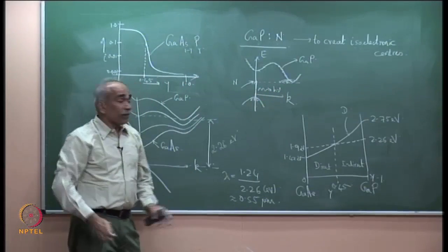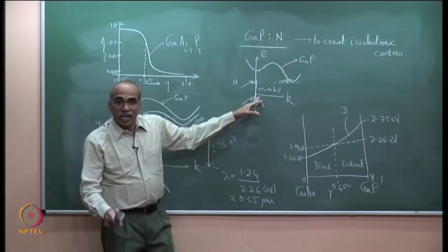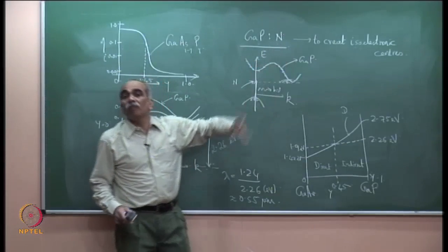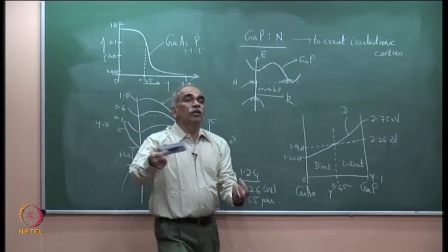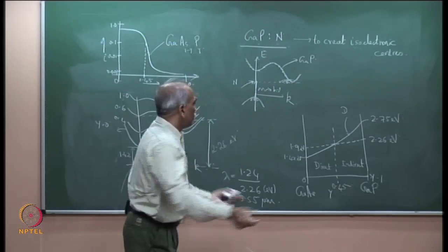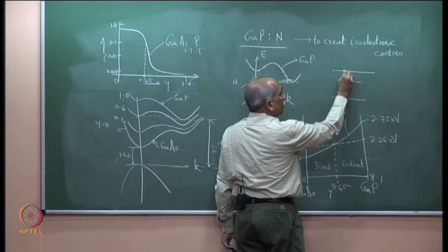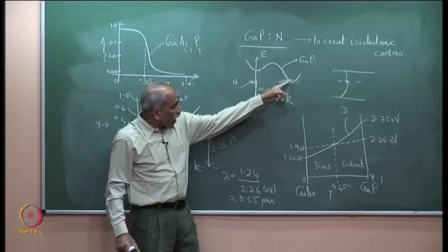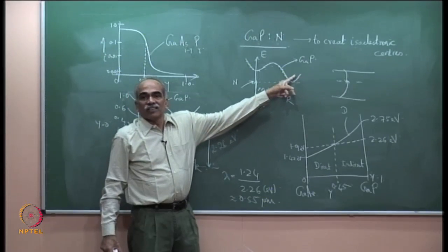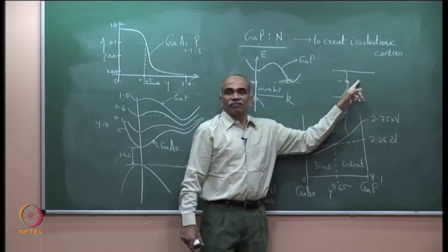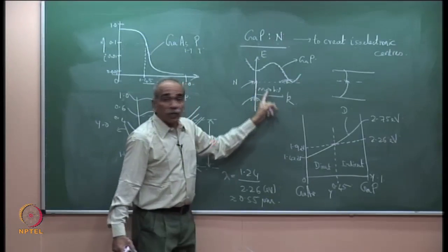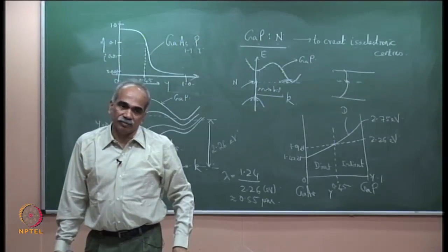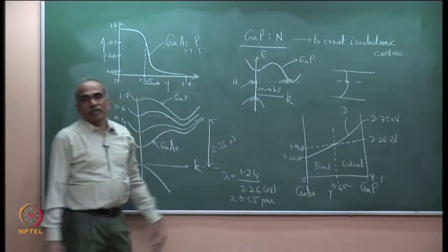The process is slow, therefore the rates of emission and absorption are slow, and you cannot make lasers by this doping by isoelectronic centers. The rates of emission and absorption will be affected because of this additional process. It is like trap centers which act as recombination centers. You know that if there are trap centers in the band gap, they can act as recombination centers. The hole and electron can combine here. It's almost like that, but the isoelectronic centers are close to the conduction band edge. Therefore, these levels actually act like trap centers. They facilitate recombination and photon emission. However, the process is now slowed down, and therefore you cannot use the same technique to realize laser diodes. But LEDs with relatively low radiance are made by this technique.